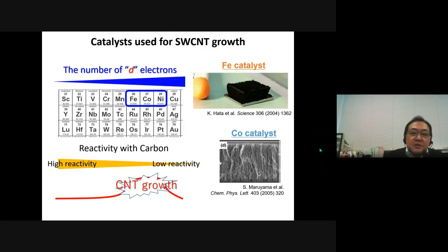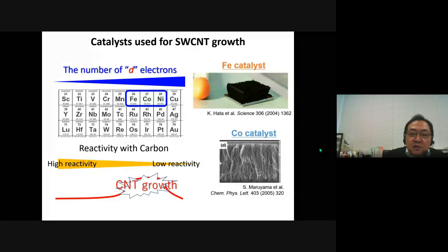To grow carbon nanotubes by CVD, iron group elements such as iron, cobalt, and nickel are widely used as catalysts. This is because the number of d electrons and their energy levels are related to decomposing the feedstock gas. The metals with a small number of d electrons have high reactivity with feedstock gas. This leads to formation of metal carbides, which sometimes results in the deactivation of catalyst. On the other hand, metals with 10 d electrons, that is, completely filled d orbitals, such as copper, silver, and gold, have low activity with feedstock, so they are not suitable to grow carbon nanotubes.